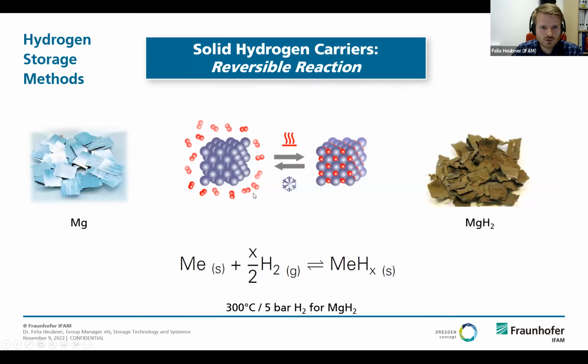To name one example more specifically, that can be magnesium that reacts with hydrogen in the gas phase to magnesium hydride. Can you see this on the slide? The reaction takes place at 300 degrees Celsius, for example, and 5 bar hydrogen gas pressure. The formation of a metal hydride, in terms of the chemical reaction, is an exothermic reaction. So heat is released during formation of the hydride.